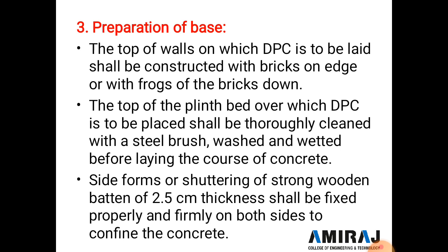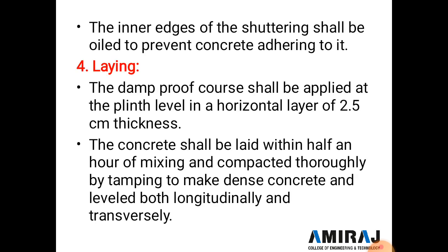Now side form or shuttering of strong wooden batten of 2.5 centimeter thick shall be fixed properly and firmly on both sides to confine the concrete, and the inner edges of the shutter shall be properly oiled to prevent the concrete adhering to it.